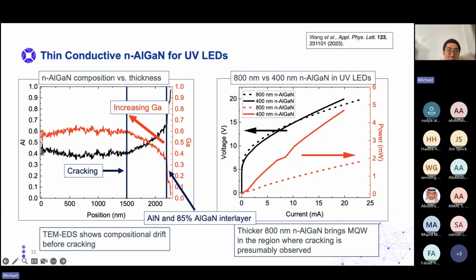So over here, this is TEM EDS, which measures the composition of the material throughout the entire structure. So you can see here, this is our aluminum nitride, which has no gallium, and then our 85% aluminum interlayer. And we start growing our aluminum gallium nitride. And as we grow more and more, the composition starts drifting up because of compositional drift.